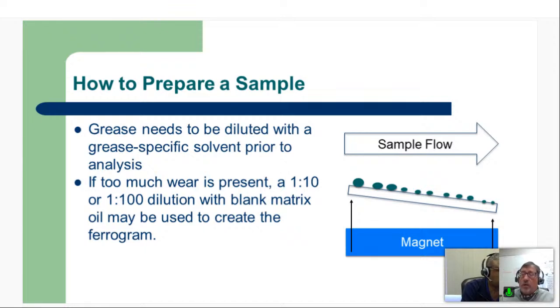Because, right, Ray, we don't want particles piling on top of each other too much and kind of hiding the story that's there. That's correct. That's why you had that tilt that you see. I told you that was the air gap in between that you need to have. And if there's just too much there, it just becomes kind of a pile or a mound. And so by diluting it to 10 to 1, 100 to 1, we get to spread those things out even more, in addition to the tilt and so forth, so we can really see what's there.